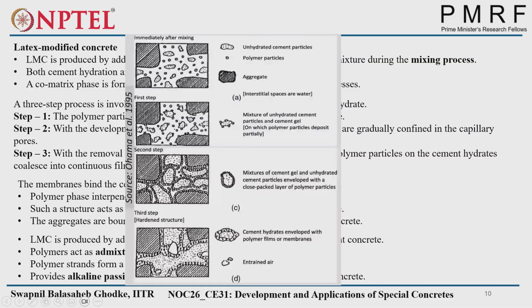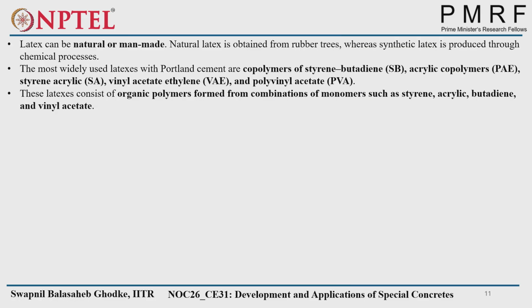Here, that layer further increases, width increases, and that width increment depends upon how much void is available in that concrete matrix. That means this is the hydrated and unhydrated cement whatever available. So this is the surrounding film formation around all the inert material as well as the hydrated material. Because of that, whatever the voids available will be occupied by this polymer film. So voids will automatically get closed. Certain amount of air still will be available, which will not fill with this polymer. But in the case of the previous polymer concrete, the air will be completely removed because we are going with the impregnation. Here, a certain amount of air will be available. So that also has certain advantages, because of the certain amount of air available, the freeze thaw resistance will be higher compared to the previous polymer concrete.